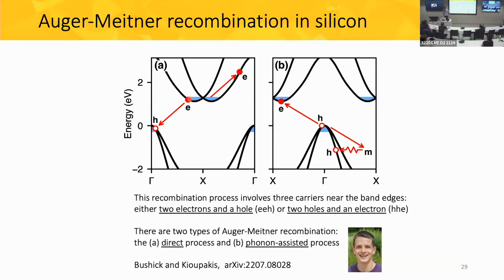The way you can think of it is an electron recombines with a hole. Now we see this in energy and momentum space. And in order for this process to happen, another electron must take the extra energy and the extra momentum. And that's a direct process. The same thing can happen with two holes and one electron, of course. However, the process can also take place in two steps, where the extra momentum coming from the phonon can enable a transition that would otherwise be forbidden. For example, in this case, when you have two holes, one recombines with the electron, the other will be scattered to this state, but you have no state to go to. So you need this phonon to bring you back to where the band is and enable the overall process. So this is the work of Kyle that you can find posted on the arXiv if you'd like to see more details.